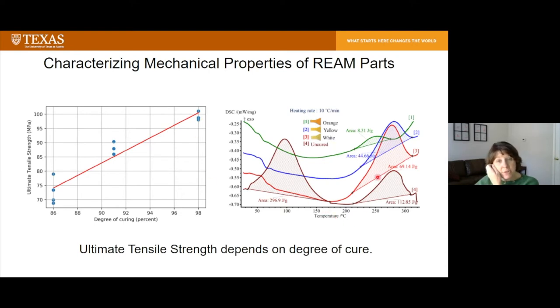And on the right here is just a DSC image of, in brown, the uncured resin. So each of these peaks indicates an exotherm. The polymerization of these resins is an exothermic reaction, so the exotherms basically document the progress of the reaction. So the uncured resin has an additional exotherm because, of course, it hasn't been cured.